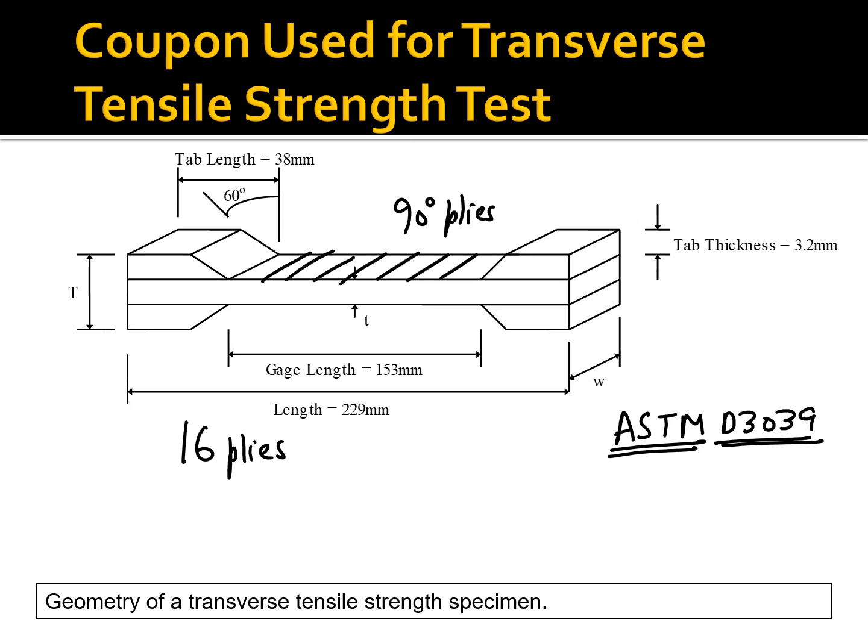So far as the strain gauge is concerned, we only need the strain gauge in the direction perpendicular to the fibers right here, and that'll be this direction. And this will allow us to find what the Young's modulus in direction 2 is, or E2. But you can always put the strain gauge in this direction as well, that is parallel to the fibers. So this is epsilon 2, this is epsilon 1.